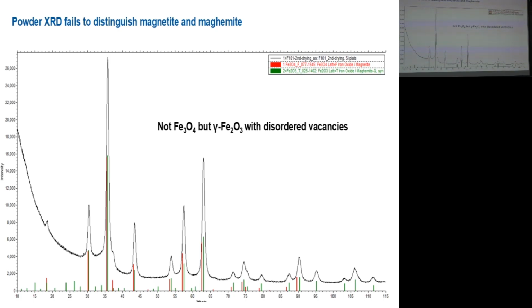And in this case, you cannot see any signature of such ordering. Actually, this sample is maghemite with fully disordered vacancies, whose XRD pattern is very, very similar to magnetite. There are some minor differences in intensities, but they will disappear in these patterns of nanoparticles. So just remember that you can't use XRD to distinguish magnetite and maghemite.